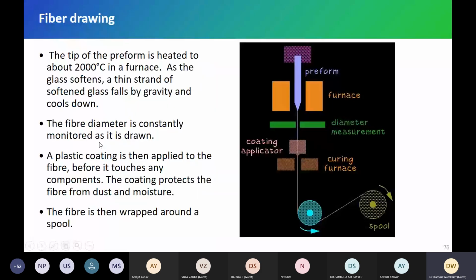Now, once your preform is ready, it is ready to draw the fiber. It is a simple process now. We take the preform, put it into the graphite furnace, and heat and increase the temperature to, suppose, 2000 degrees Celsius. What happens when you heat is that the tip of this preform, which is a glass rod, melts down, and because of gravitation it comes down. That part we catch manually, and then manually pull it down.